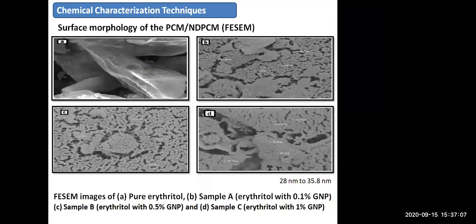Then chemical characterization techniques. The surface morphology of the PCM, the microstructure and the morphology of erythritol with 0.1%, 0.5%, and 1% graphene nanoparticle samples were investigated by field emission scanning electron microscope analysis, the FESEM. The size of the nanoparticle sample was found to be 28 nanometer to 35.8 nanometer. The SEM images show that the graphene nanoparticles are randomly distributed and hold the nanoparticle in a fixed position.